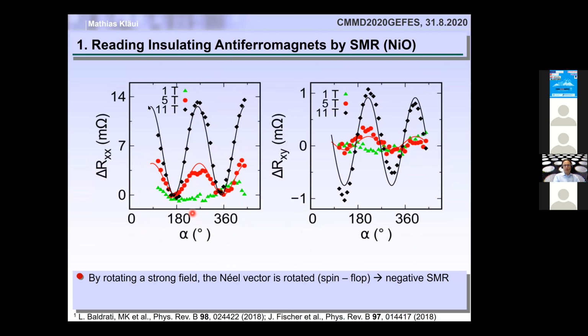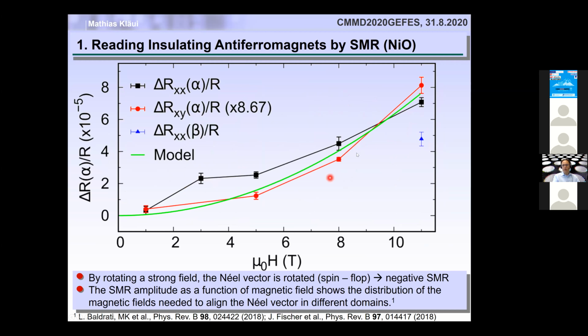And we saw that indeed, if you apply a strong field like 11 Tesla to reorient these sublattices, we can get this sine squared dependence that we expect. And if you have a lower field, then essentially you cannot rotate the sublattices due to some anisotropy and pinning. And then you can actually apply a stronger and stronger field and see how much of the sublattices reorients.